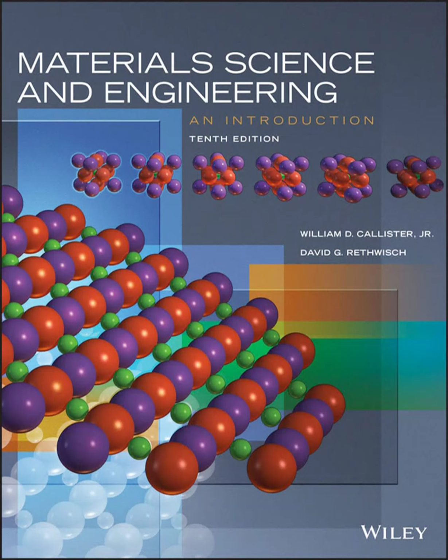Above a certain point, we call it the Debye temperature, θ_D, the heat capacity actually levels off. It becomes essentially constant. So even if the material is getting hotter, the amount of extra energy needed to raise it 1 more degree stays the same? Pretty much, yeah. Beyond that Debye temperature, for a lot of common solids at room temperature, this value is roughly 25 joules per mole Kelvin. It's a surprisingly good approximation.